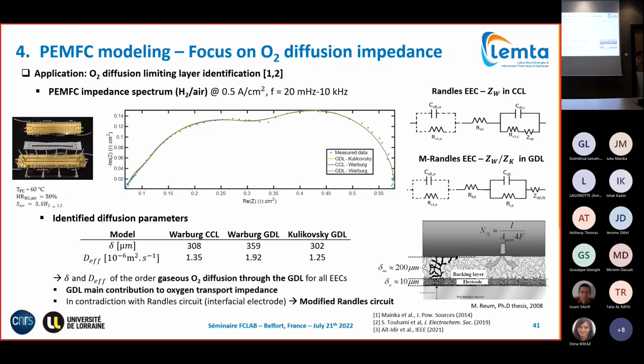And what you see is that in all three cases independently, your characteristic diffusion length is closer to the thickness of the GDL than to the thickness of the active layer, and orders of magnitude higher than the ionomer layer covering the active sites, which is on the order of nanometers. As well, the effective diffusion coefficient is close to gaseous oxygen diffusion.